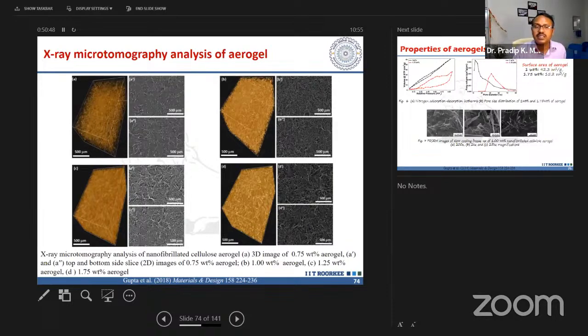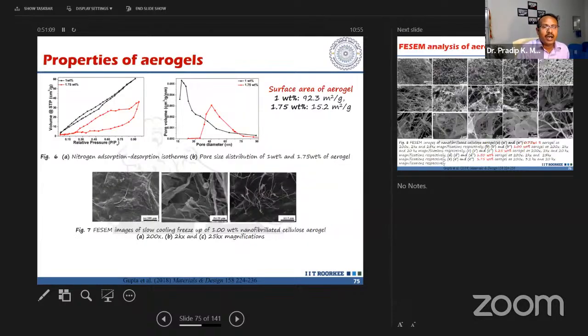This X-ray microtomography analysis shows the 2-dimensional as well as 3-dimensional structure of the material. You can see the cellulose fibers. Try to realize, it is not generated by software and it is not simulated data. It is the scanned data of the original material. We have also checked porosity, and it is very, very high, at 1 weight percent and 1.75 weight percent, in the mesoporous range.